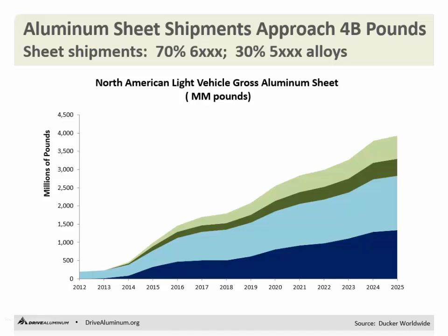Now, the question always comes up, well, how much aluminum will be needed to support all this growth? And this is the growth curve for aluminum sheet from 2012 out to 2025. In 2012, there was about 200 million pounds of aluminum sheet consumed in the marketplace. That grows to about 4 billion pounds by 2025, and a fairly steady growth rate. The blue material is heat treat stock, 6061, 6000 series typically, and the green is non-heat treat material, typically 5000. So the combined total, almost 4 billion pounds of growth between now and 2025. And the sheet producers are prepared and able to support this growth with the necessary new investments to support this level of demand.